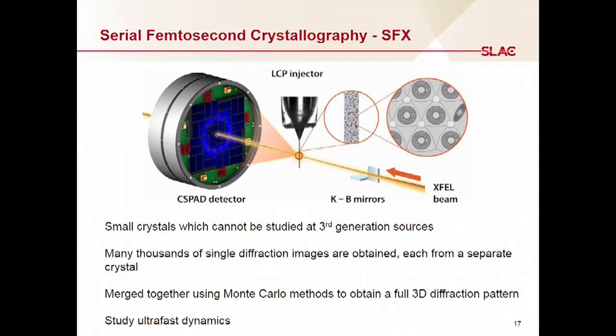If you have a very, very huge crystal, you certainly have regions which are very excited, but then because the optical laser is attenuated throughout this crystal, you cannot necessarily get a very high percentage of excited states. And so these small crystals are extremely important for studying these ultrafast dynamics.